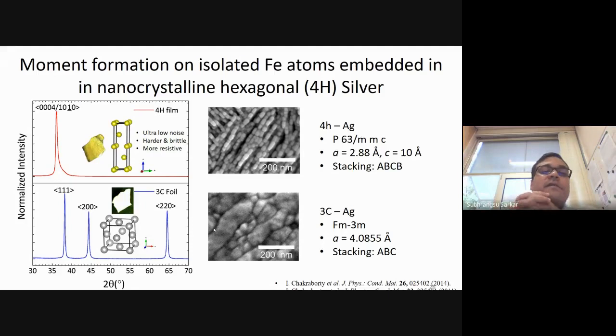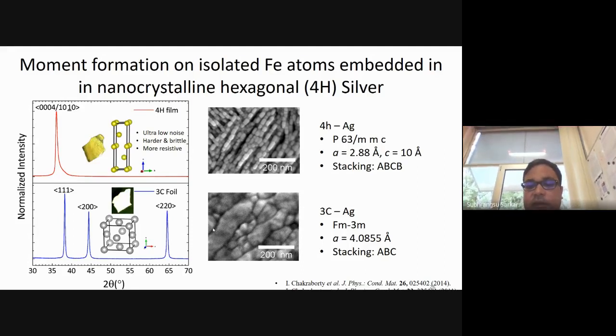After doing X-ray diffraction and careful investigation by transmission electron microscopy, we found that the crystal structure of this new kind of silver is no longer cubic, it is actually hexagonal. By hexagonal, we mean that the lattice constants along different directions are completely different. Earlier, the cubic silver had a lattice constant of about 4 angstrom, and now it has completely changed. The symmetry of the system has also changed.